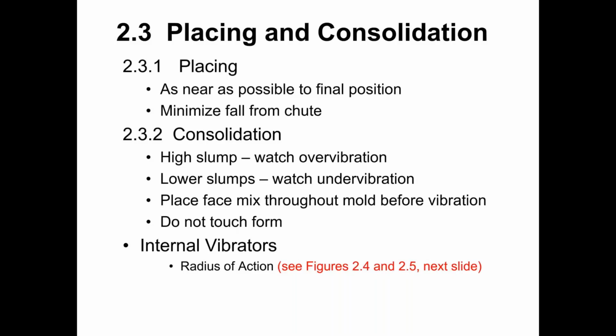Now, both of these rules of thumb primarily apply to normal slump mixes. If it was a self-consolidating mix, then generally, depending on the product that's being cast, we're going to pour the product from one location and allow the concrete to flow and fill the form, because that is the process of self-consolidation. It's the energy of the flowing concrete as it fills the form that's helping to consolidate the concrete. All right, so these rules of thumb here on the slide are for normal slump mixes. For flowable mixes or self-consolidating mixes, placing it as near as possible to its final position isn't really something that we would try to do. We would want that concrete to flow so that it gets consolidated. Whether it's a normal slump mix or a higher slump mix, we still generally want to minimize the fall from the chute, just so when the concrete splatters on the form, it doesn't segregate.